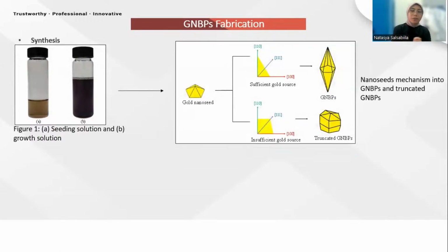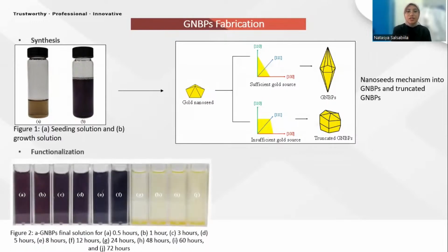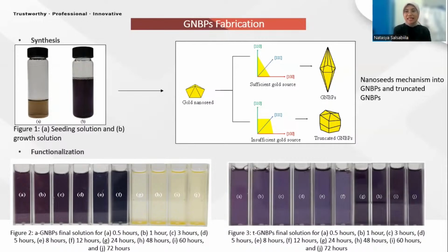For synthesis, there is a mechanism of growth from seed. So an increasing time leads to a decrease in gold source, which affected the production of truncated GNBPs, and GNBPs cannot grow in perfect shape. Figure 2 shows the GNBPs or amine functionalized GNBPs for 0.5 until 72 hours. It can be seen here that after 12 hours, the solution turned light yellow. Figure 3 shows the GNBPs or thiol functionalized GNBPs for 0.5 until 72 hours. So it can be seen here that after 12 hours, the solution turned darker.